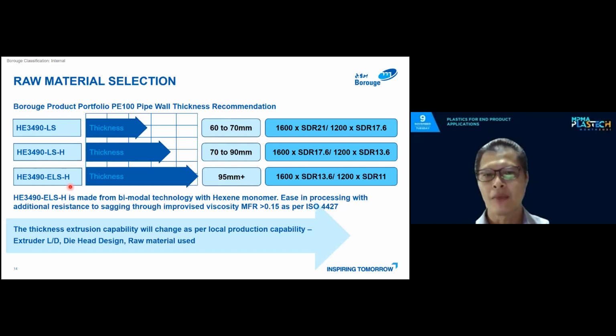This grade is made of bimodal technology with hexene monomer. The ease of processability, in addition to the resistance of sagging, is through this improved viscosity MFR that we have seen. There is a more than 0.15 provision given in the ISO 4427. Again, I must stress that the wall thickness capability changes per local production capability. That means if your machines are able to make this size, as well as the raw material used, coupled with the operator skill, a good large diameter thick wall pipe can be achieved.